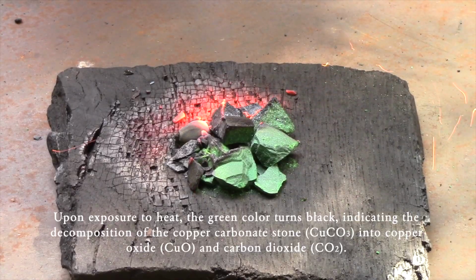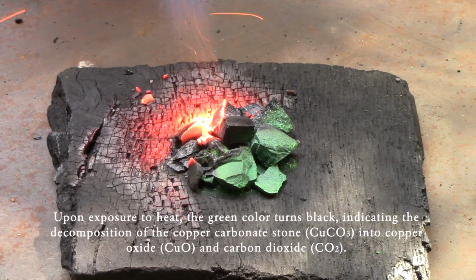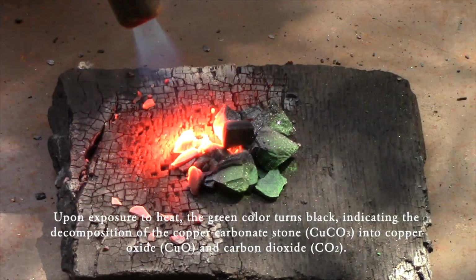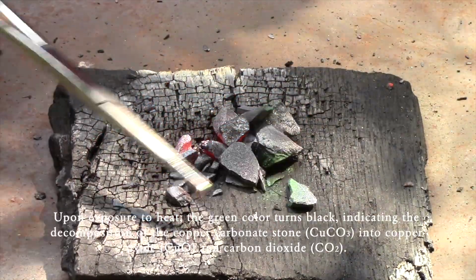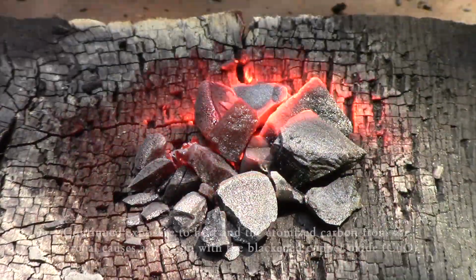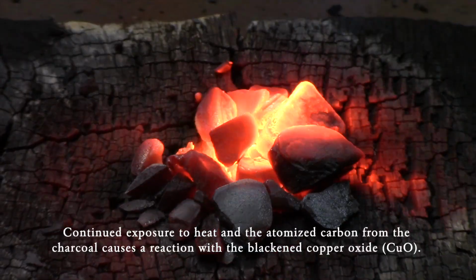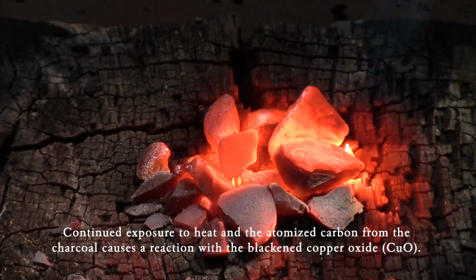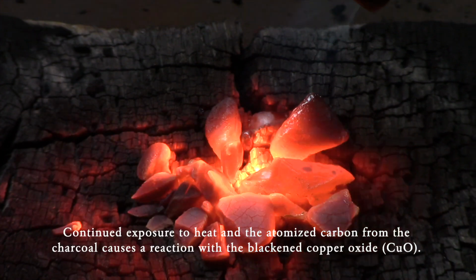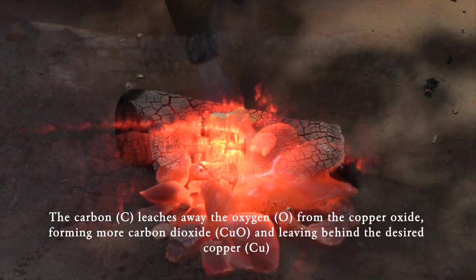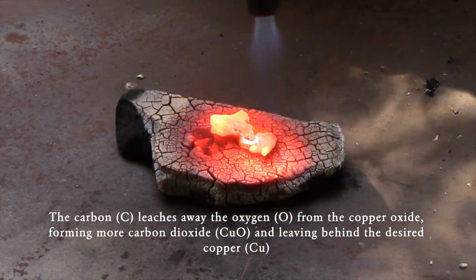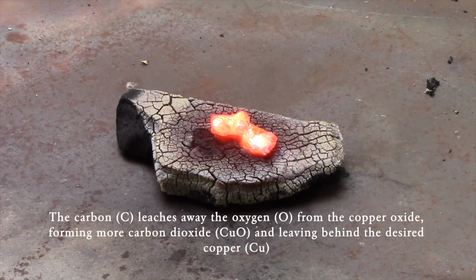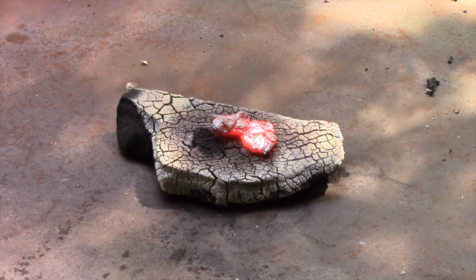Upon exposure to heat, the green color turns black, indicating the decomposition of the copper carbonate stone into copper oxide and carbon dioxide. Continued exposure to heat and the atomized carbon from the charcoal causes a reaction with the blackened copper oxide. The carbon leaches away the oxygen from the copper oxide, forming more carbon dioxide and leaving behind the desired copper.